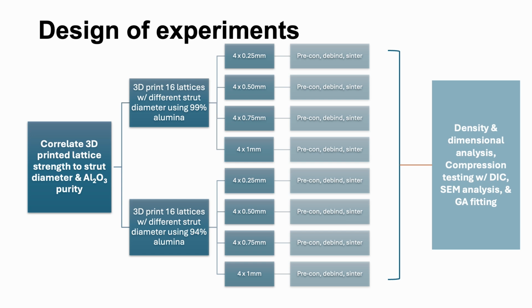Every single lattice was put through the entire thermal post process, and all samples were characterized using density and dimensional analysis, compression testing with DIC, which is digital image correlation, SEM analysis, and the Gibson-Ashby model fitting.